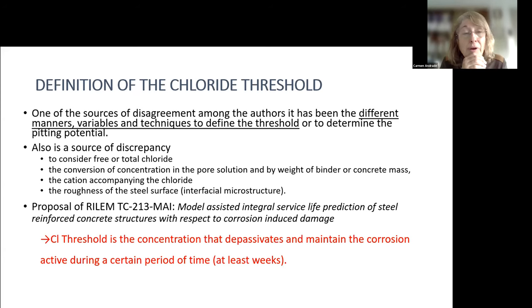Well, the other point is about the definition of the chloride threshold, because this is one of the sources of disagreement among the authors. There have been different manners, variables, and techniques for defining this threshold and for determining the pitting potential. In that case, it's normal to have a distribution, to have different values, but we need to distinguish whether they come from different tests or from the same test, but repeated. And as far as I know, only Hausmann, after Bright and after us, that I will present, did experiments, and now Federica, I think that, well, you didn't repeat in the same bar, but repeated with the same type of specimen, several specimens.